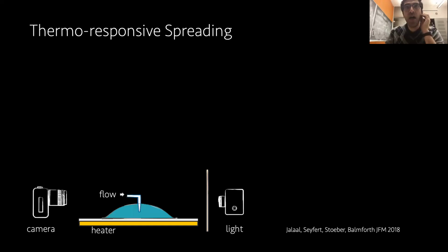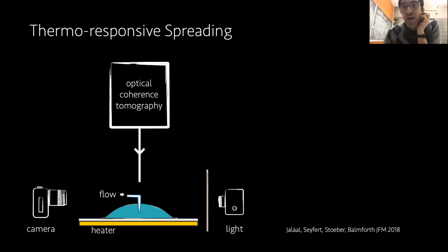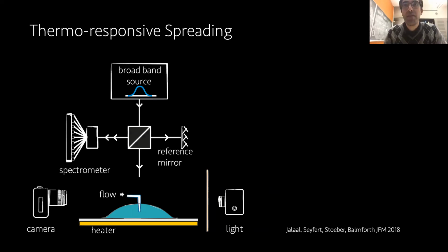Okay, so what we've done in our setup, we did pretty much the same thing, camera and the light. We now inject the fluid, but we also have a heater to heat this fluid from the bottom to basically turn it viscoplastic, to see if we can control the spreading. We also did something else, actually. On top of this spreading droplet, we put a device, we use an optical technique called optical coherence tomography. For the experimentalists in the audience, this is basically an interferometer using white light, which does the interference of all the wavelengths of the white light, and through that gets information in depth.